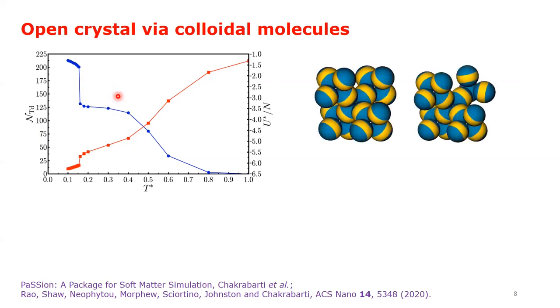Note that the crystal structures are stable even in the absence of a hierarchy of interaction strengths when we have A tri-block patchy particles rather than AB.